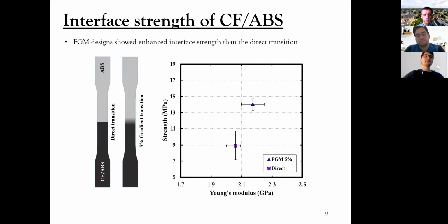Because we have CF ABS, the matrix material is the same, and ABS is just a simple ABS material. We designed and tested these similar interfaces, and results reveal that although the matrix material is the same, the sharp transition of material properties increases the stress concentrations, which reduces the strength and stiffness of the part. Likewise, gradual change of material properties increases the strength around 58% and stiffness around 6%.